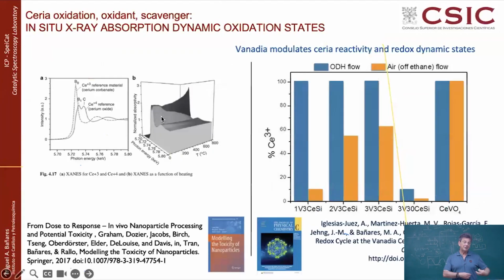Now, what is happening is that the ceria in the body is getting continuously reduced because it is oxidizing the environment. But because inside the body the supply of oxygen can be limited here and there, little by little, ceria is making an oxidative stress damage, but then it's being reduced until it's no longer making damage. And then you can also see this evolution, because at the beginning it is being reduced because it's oxidizing the environment until it levels off.